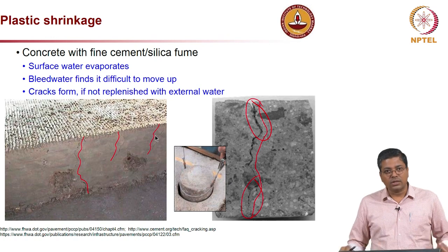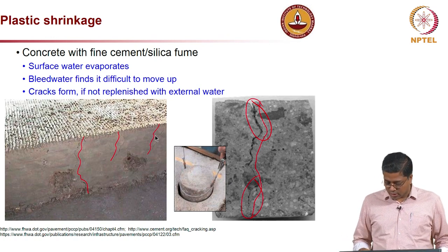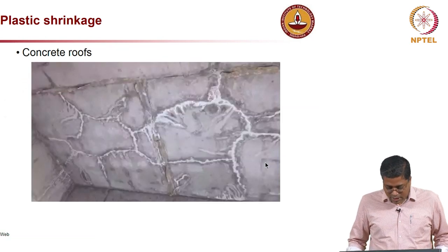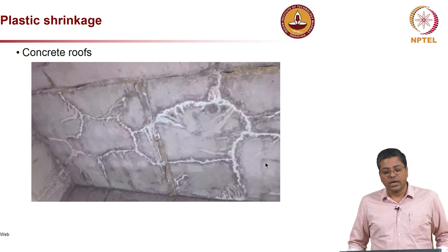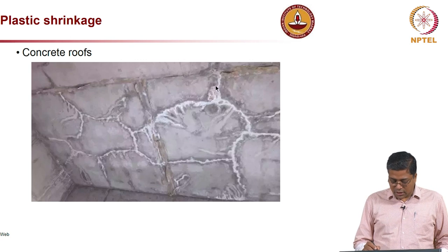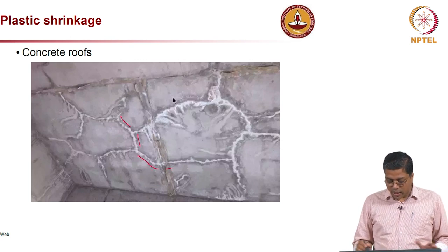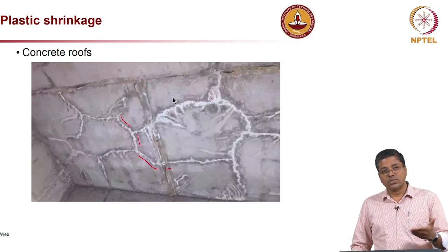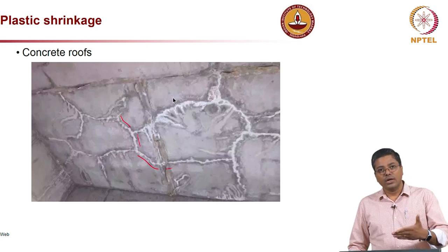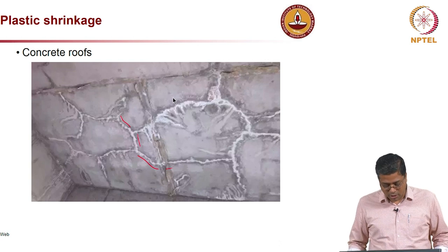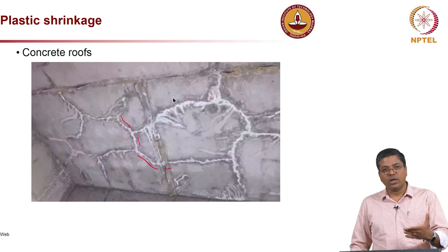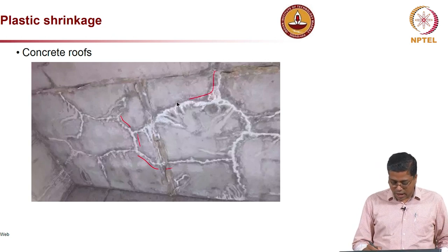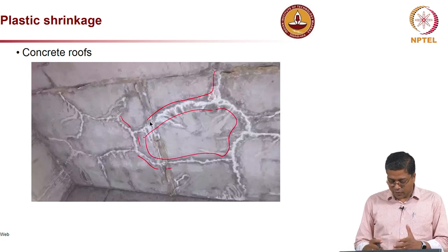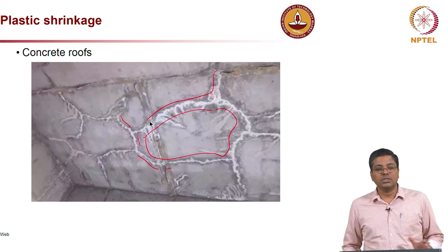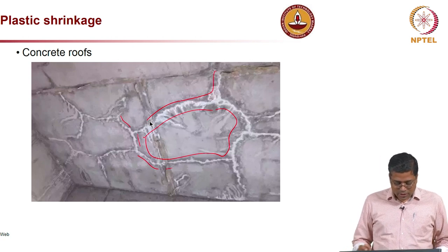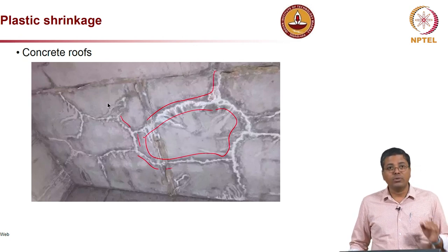So, the top surface or near the top surface cracks more than the underneath. And this is another example of a roof structure where significant shrinkage cracking was observed. You can see a lot of cracks over here, and these white patches which you are seeing are actually the water from the moist curing. The top surface of the same slab, the curing water, seeps in and through these cracks which are present, and then the salts are leaching out, and you can see this white patch on this surface. Sometimes you can even see long crystals being formed through this crack.